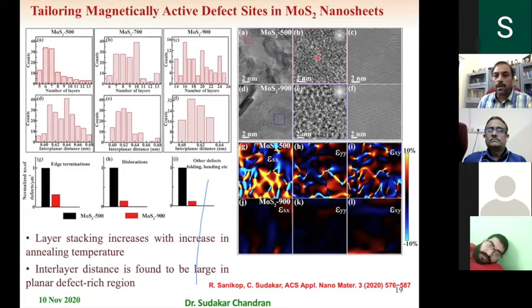In spite of that, what you can strikingly see is if you take the high resolution image and then also calculate the strain involved in the lattice fringes, the 500 degree sample has a lot of strain. The strain mapping, derived from these fast Fourier transform filtered images, shows that the 500 degrees Celsius annealed sample has large strains, whereas the strain is pretty much not there in the 900 degree annealed sample.